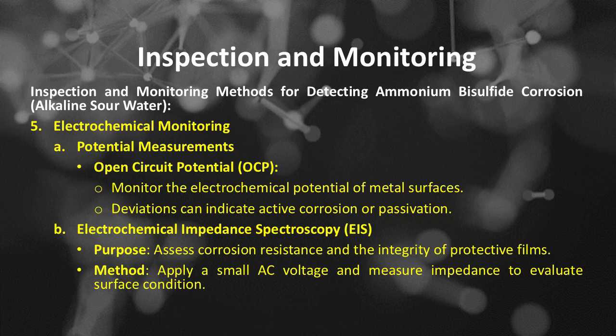Inspection and monitoring methods. Number 5 is electrochemical monitoring, which includes, number A, potential measurements, open circuit potential or OCP, to monitor the electrochemical potential of metal surfaces; deviations can indicate active corrosion or passivation. Number B, electrochemical impedance spectroscopy or EIS. It is purposed to assess corrosion resistance and the integrity of protective films. This method applies a small AC voltage and measures impedance to evaluate surface condition.